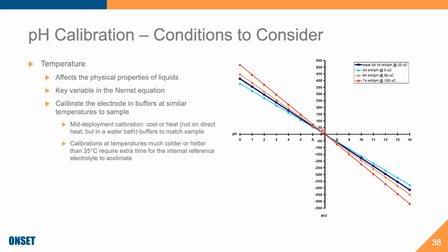So when you're calibrating, and I'm going to show what I'm talking about in just a second, it's important to calibrate close to what you're expecting your sample to be. If you're mid-deployment and you're out in the field, for instance, maybe you're up in Colorado and you're doing acid mine drainage, you would ideally calibrate your electrode at the same temperature that the water is currently at. It's not necessarily the same temperature as the air. What it is the same temperature as is the solution. So you can either soak your buffers, float them in the water that you're testing just to get them to equilibrate, or you can cool them or heat them. Do not put them on direct heat, but get them close to at least the temperature so that you're seeing the same activity.